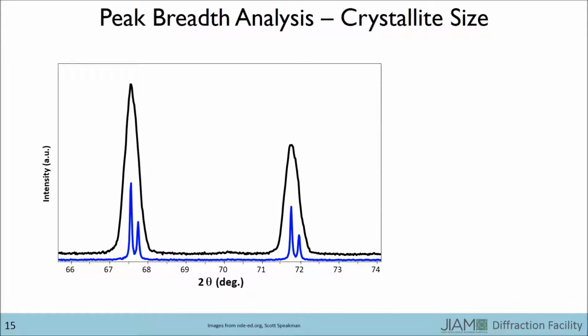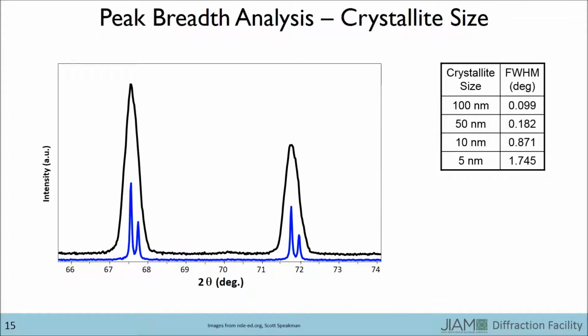Phase quantification utilizes peak intensities. We are able to obtain information from the breadth of the reflection too. For instance, if we have crystallite sizes of 100 nanometers, the full width half maximum, or FWHM, of the reflection should be around 0.1 degrees. If the crystallite size is reduced to 5 nanometers, the full width half maximum should be around 1.75 degrees.